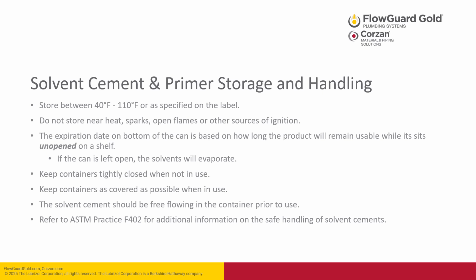When working with solvent cements and primers, there are several things to keep in mind with respect to storage and handling. You'll want to store the products between 40 and 110 degrees Fahrenheit, or as specified on the label. Do not store solvent cements or primers near heat, sparks, open flames, or other sources of ignition. Remember that the expiration date on the bottom of the can is based on how long the product will remain usable while it sits unopened on a shelf. If the can is left open, the solvents will evaporate and cause the cement to no longer be useful.